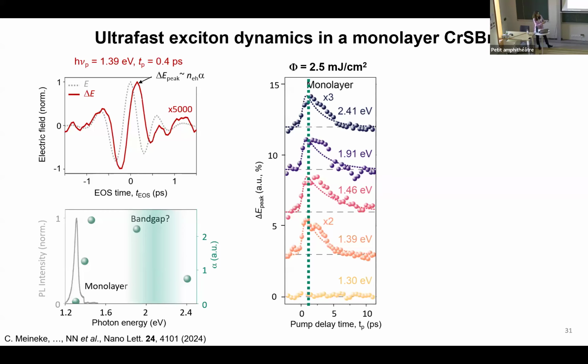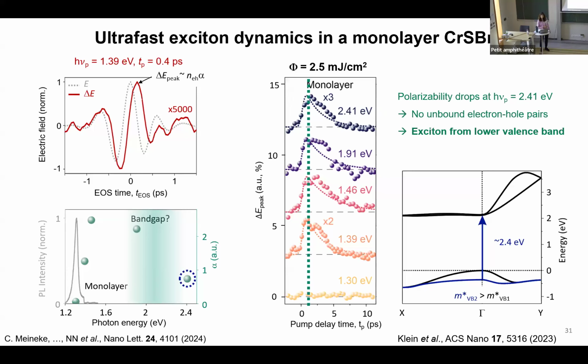However, when the photon energy grows and we start to generate slightly more and more free electron and hole pairs, the polarizability grows. It has a more or less plateau-like behavior all the way up to 2 electron volts. However, again, at 2.4 electron volts, the polarizability is quenched. So it seems that we start to form another series of excitons. Why is this happening? It is sufficient to take a look at the band structure. We see that the valence band is composed of a topmost valence band and another one lying deeper in energy. We believe that when we shine a 2.5 electron volt radiation to our monolayer, we are photoexciting electrons from this second valence band to the conduction band, and therefore they start to form another series of excitons.